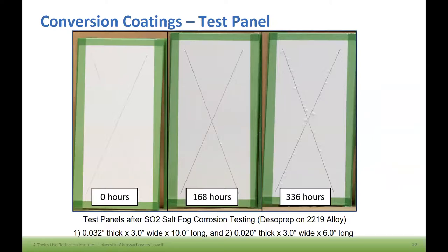This shows the test vehicle that we use for the conversion coatings, just simple test panels, two different sizes. One's 3x10, one's 3x6, and it was scribed. And this just shows an example of test panels after we did some SO2 salt fog corrosion testing on the DesoPrep conversion coating on the 2219 alloy. So you can see after 336 hours, we've got a lot of propagation of corrosion outside of the scribe area. So this just shows the progression and the propagation of that corrosion over time.